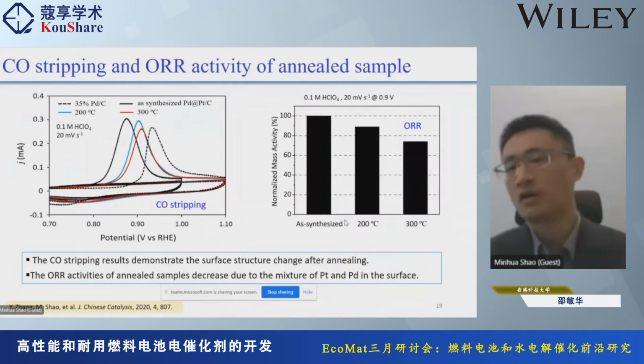So basically, at a high temperature, you already form this kind of alloy surface, and we define this temperature as about 150 to 200 degrees C, where it already starts. So when you prepare the ink, you have to make sure that the local temperature cannot be that high. Otherwise, your core shell structure will be damaged.